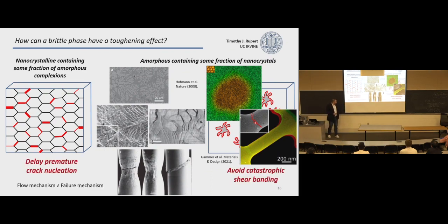The main point here is that the flow mechanism or the plasticity mechanism is not always the failure mechanism. So we're able to delay premature crack nucleation. And in this side, they're able to avoid catastrophic shear banding. But in both cases, that's okay. You're going after what's that failure mechanism, not just what starts to move plasticity.